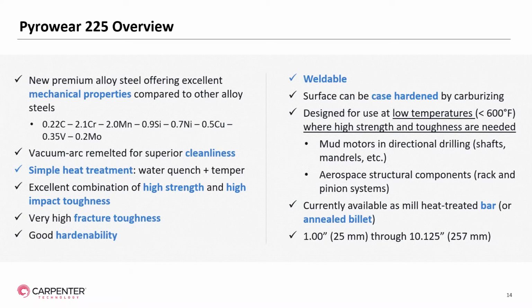This alloy can undergo a very simple heat treatment of water quenching and tempering. It does not need to be air cooled or oil quenched. Its claim to fame is that it offers an excellent combination of high strength and high impact toughness, as I'll show here in a couple minutes, coupled with very high fracture toughness and very good hardenability. The alloy is weldable, and it is case hardenable by carburizing. It is designed for low temperature use, that is temperatures less than about 600 degrees Fahrenheit, where high strength and high toughness are both needed.